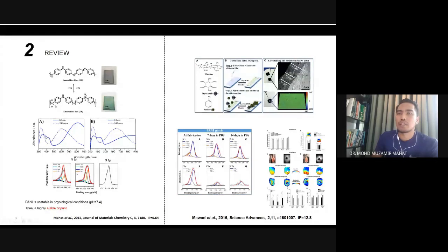Meanwhile, for the conductive one is 3 bumps. So the bumps are representing a different chemical structure to this polymer. Okay, this is non-conductive, which is the blue one. We call it emeraldine base. Once we introduce acid within the system, it becomes emeraldine salt. So this emeraldine salt, if you see,